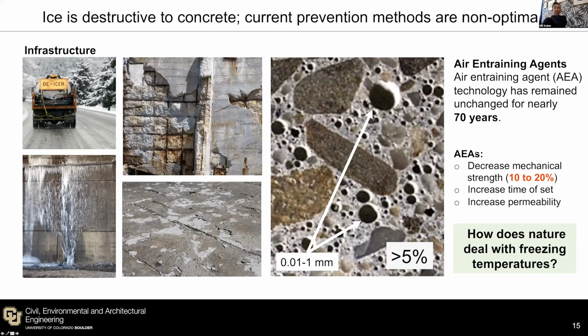So these air entraining agents are really good at alleviating this pressure, especially if you have more than 5% of air entrained in your concrete. It does really well. And so for freeze-thaw climates like Boulder, like Colorado, where we see a lot of freezing and thawing, this works quite well, but it has some downsides.